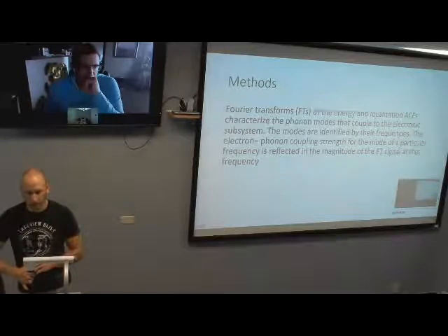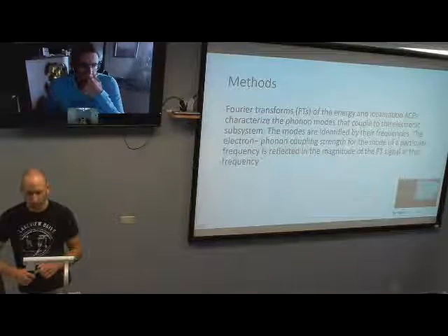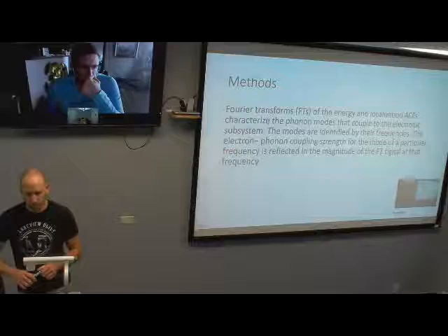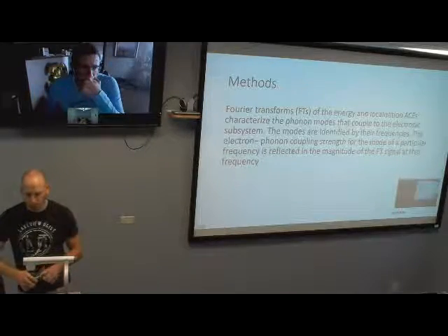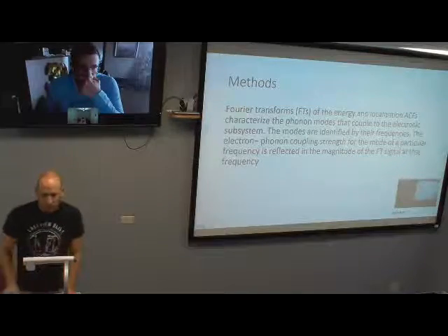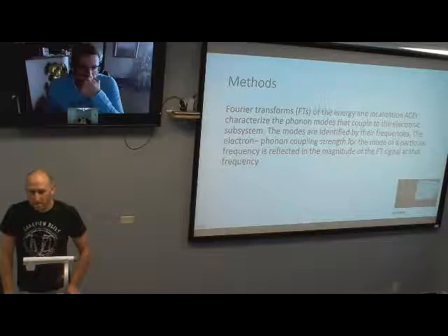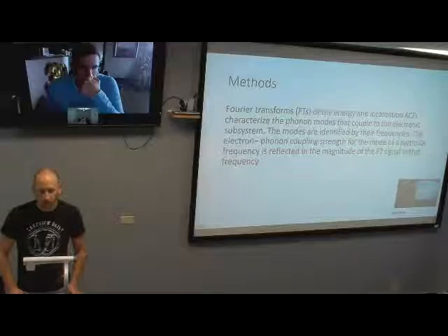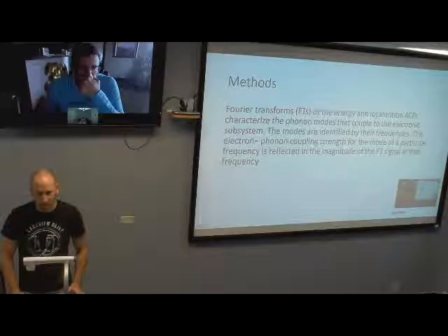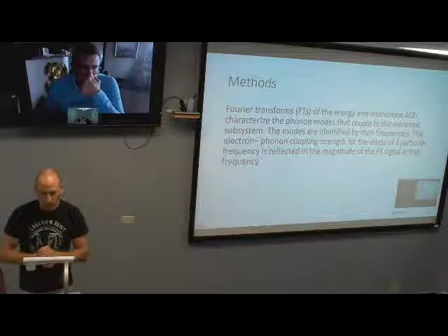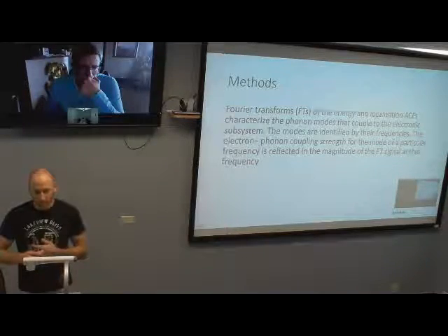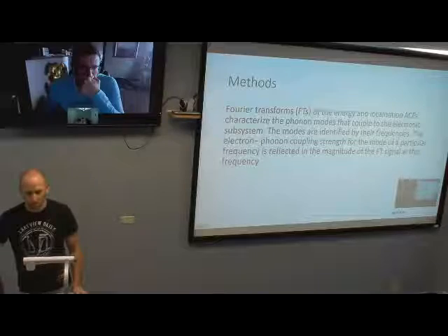Second, they find only frequencies of those vibrations which are coupled to the electronic degrees of freedom, to those energies with the i, j indexes, which Levi had in his draft, in the E they really consider for this autocorrelation function. They don't sum these energies over all states; they specify particular states when they construct the autocorrelation function. So they find frequencies only coupled to these electronic degrees of freedom. And it's not really normal modes, because normal modes correspond only to the harmonic solution. They found actual frequencies of whatever motion of nuclei at this temperature, which of course you can connect to normal modes.